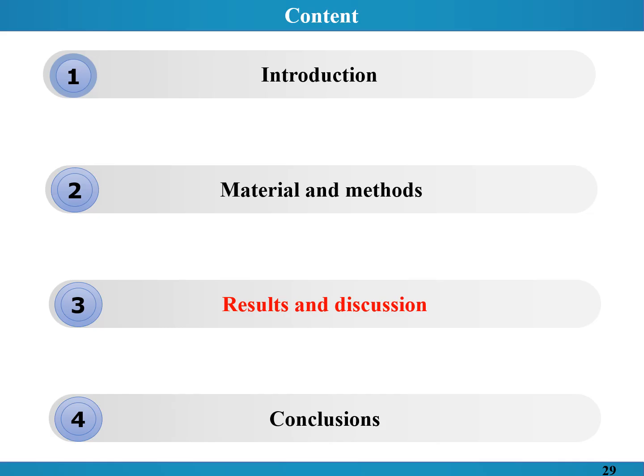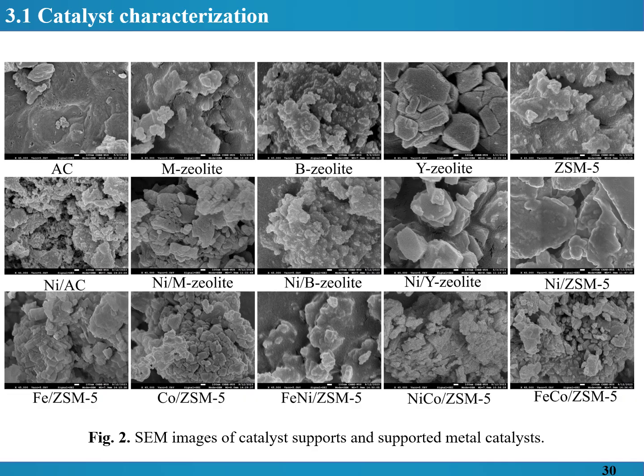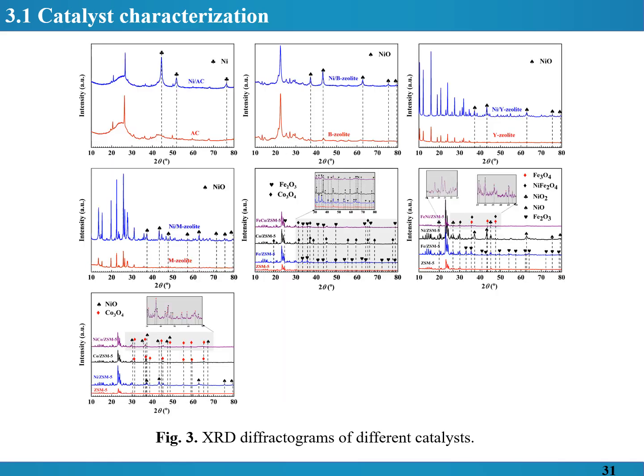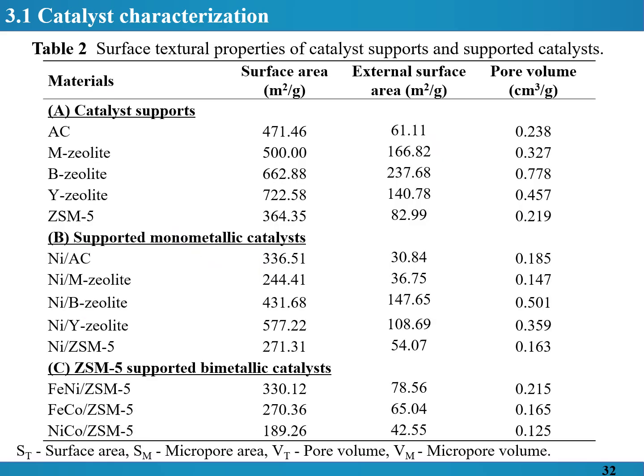The third part is about results and discussion. Figure 2 shows the SEM images of different catalysts. As the images indicate, the introduction of nickel or cobalt dopants didn't lead to significant alterations in the morphology of the catalyst. Figure 3 shows the XRD spectra of different catalysts. Table 2 shows the surface textural properties of catalyst supports and supported catalysts.